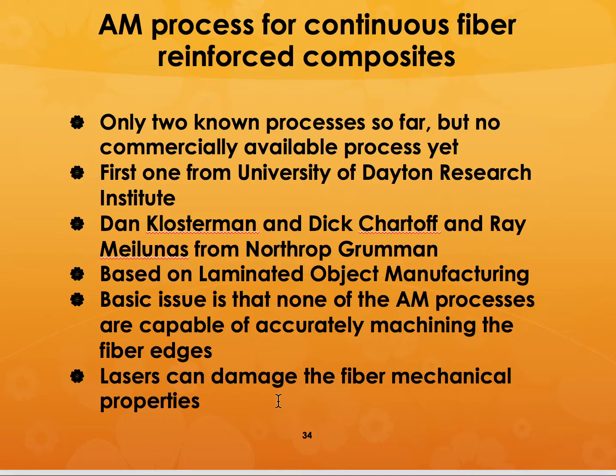For continuous fiber reinforced composites, there are only two known processes so far, but no commercially available process. First one is from UDRI, where Dan Klosterman, Dick Chartoff, and Ray Meilunas from Northrop Grumman. And Ray Meilunas doesn't work at Northrop Grumman anymore. He is at Navair, Pax River. They did something based on laminated object manufacturing, and the basic problem is that none of those AM processes are capable of accurately machining the fiber edges, so you can't really cut them off that easily. And if you use lasers, it can easily damage the fiber mechanical properties.